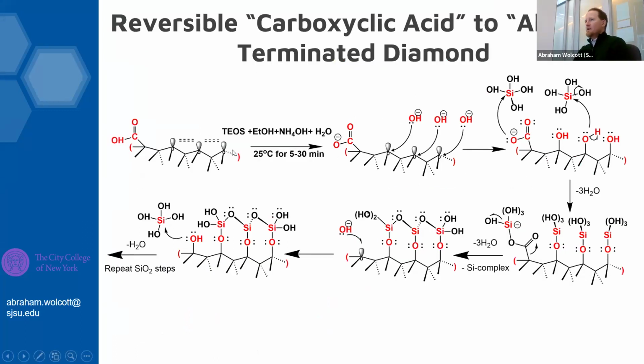So again, this is metastable, so we could reverse it. We could add a base, our ethanol, ammonium hydroxide, and water to rehydroxylate. And if we wanted to go back to our carboxylic acid and purge the alcohols off, we would do an acid treatment. Usually people do a 0.1 molar HCl treatment for about 24 hours, and then you get what's known as a carboxylic acid rich sample. It's about 7% acids across the surface of our HPHT. So this is important to reverse the process based on simple chemistry.